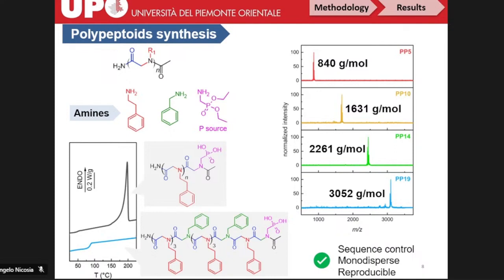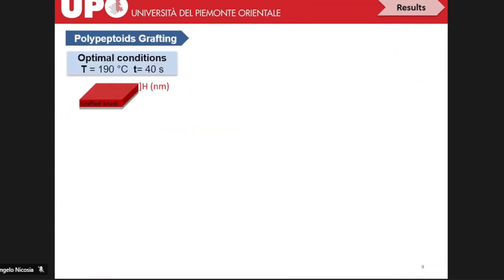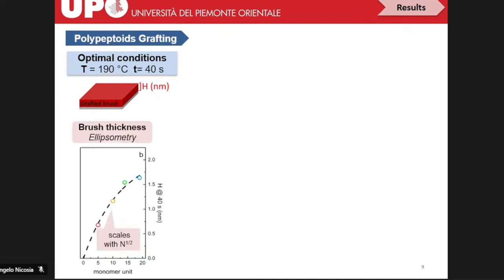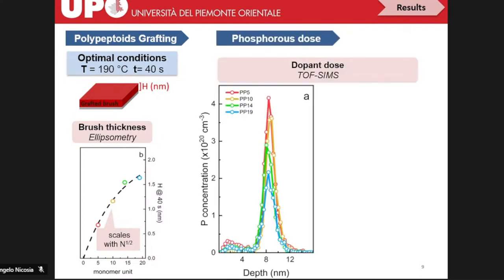Then these 4 polypeptoids were grafted on a silicon substrate. We established the optimal conditions, and we found that the film thickness increased as a function of the monomer units. Then, by ToF-SIMS analysis, we confirmed again that if we increase the molecular weight of our polymers, the concentration of phosphorus will be reduced.